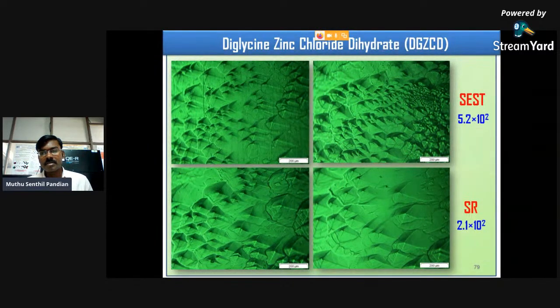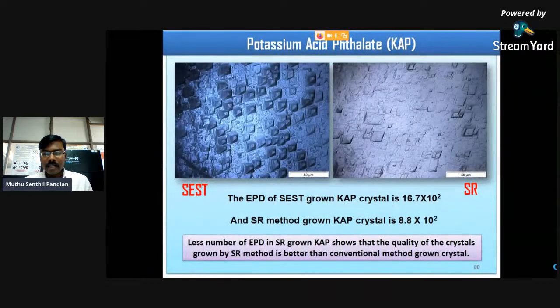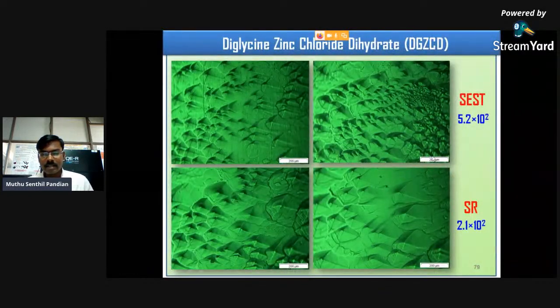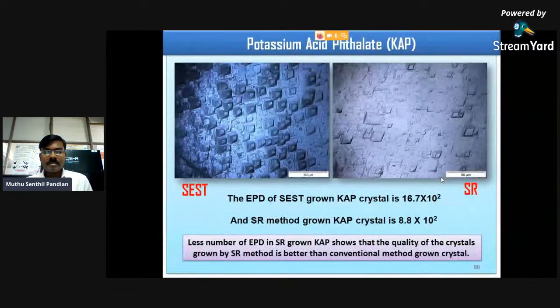Dislocation density of the conventional method grown crystal is 5.2 × 10^2 cm^-2. But in the case of SR grown crystal, it is 2.1. Here we can easily see that the number of etch pits in the conventional method grown crystal is very high compared to the SR method under identical condition. This is under identical condition, under identical scale, the etch pit density.